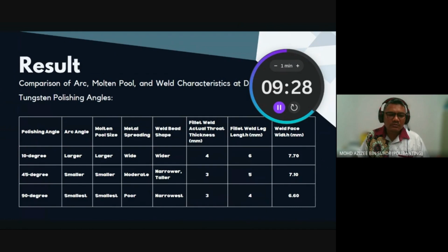The result. There are several key findings. The 10-degree polishing angle resulted in a large arc angle and significant molten pool expansion, leading to the formation of a wider weld bead. Measurement: fillet weld actual throat thickness is 4 mm, fillet weld leg length is 6 mm, and weld face width is 7.70 mm.